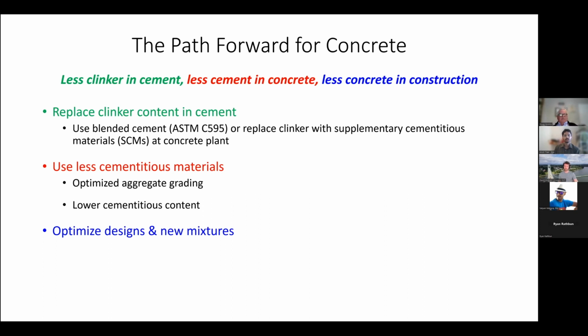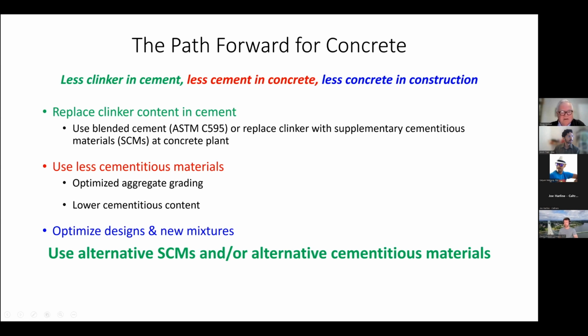Where we want to go, and it was already mentioned in the previous slides, we want to use less clinker in cement. We want to use less cement in concrete. We want to use less concrete in construction by optimizing. It's a little tougher for pavements, but for buildings, there's ways of optimizing design to use less concrete. And so, as was mentioned, use blended cements, including Type IL cements, or replace clinker with supplementary cementitious materials at the concrete plant. You can use less cementitious materials by optimizing aggregate gradations and lowering the cement content as a result. And we can optimize designs. So you can use alternative materials, as was mentioned.